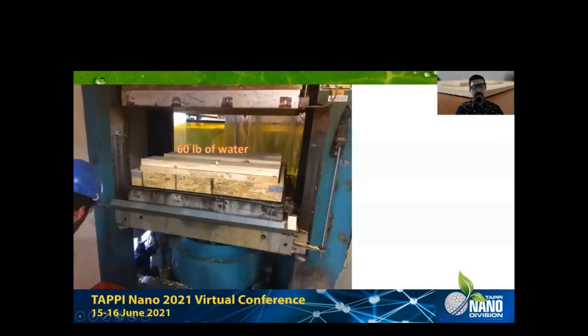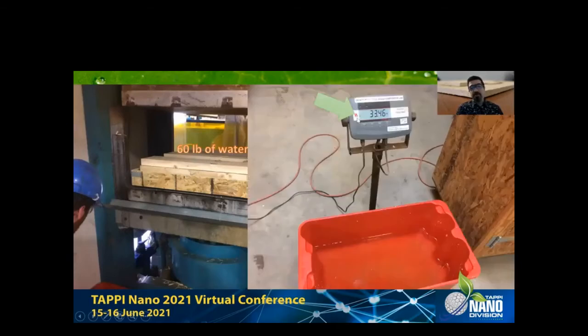So we tried this on a larger scale. This is a trial to do a 3 by 3 feet panel production, the same way, mixing them together and then forming them into a form. And then you put this in a cold press to apply pressure. This mixture has about 60 pounds of water in it, and you do contact dewatering in a matter of about a minute or so. You get about 33 pounds of that water out. And this water basically doesn't have any nanocellulose in it.